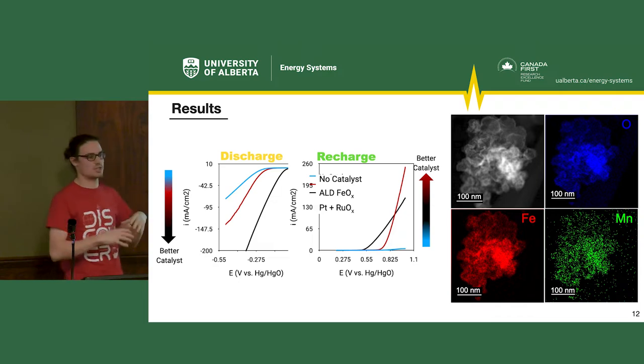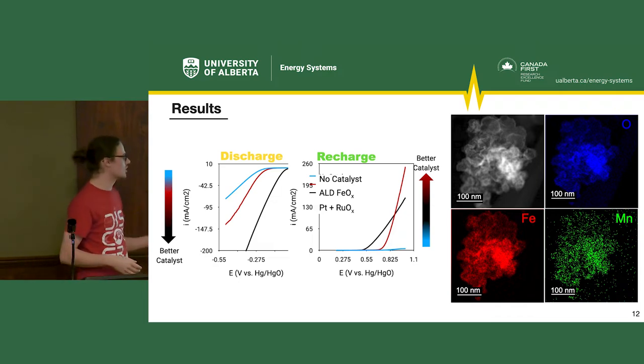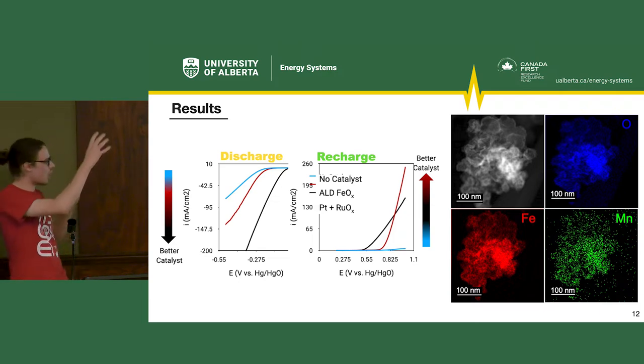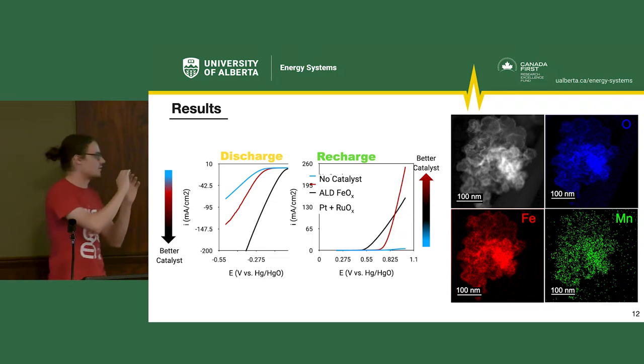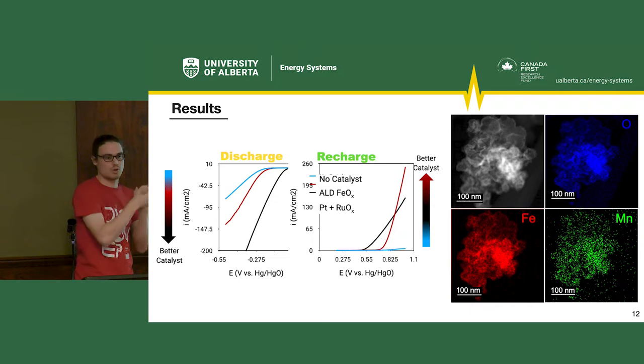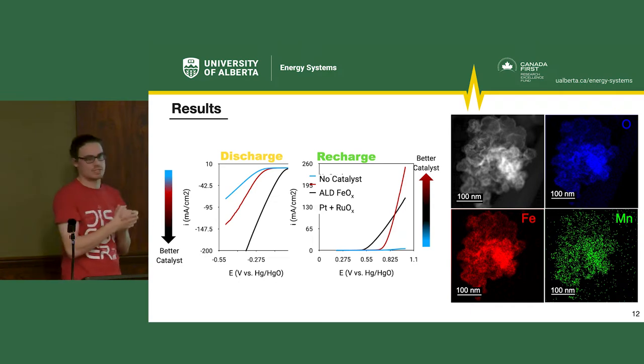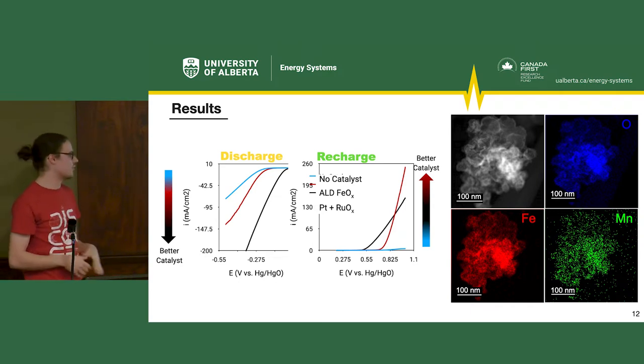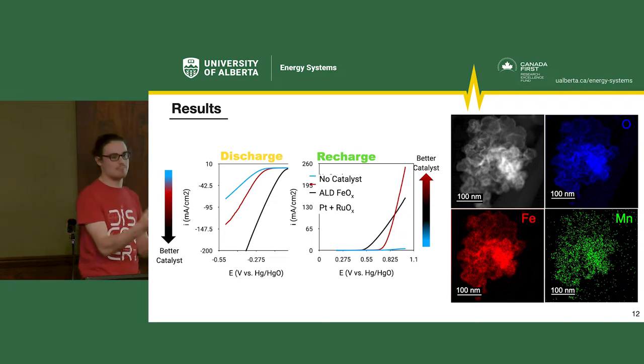So the white is just the carbon particles of my air electrode. And then blue is oxygen, red's iron. And you can see that the oxygen and iron are overlapping, and we get that thin coating around all the particles that I showed earlier in my schematic. So I'm getting what I should have. And there's some manganese signal as well because of that buffer layer I used.